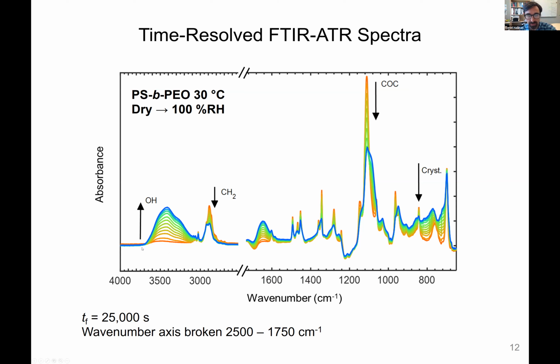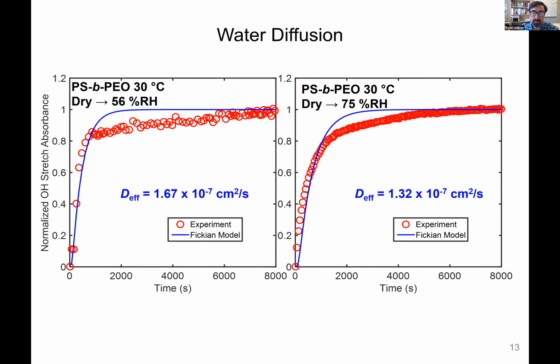We can then integrate the area underneath the water stretching peak, for example, is the one we focused on, and plot that value versus time. Because we care about transport and not the absolute value, we typically normalize it. So each one of these data points is from an integration of a spectrum that's been collected over time.